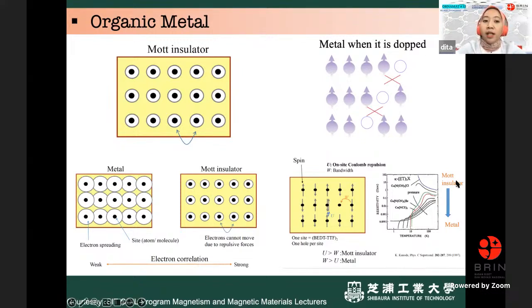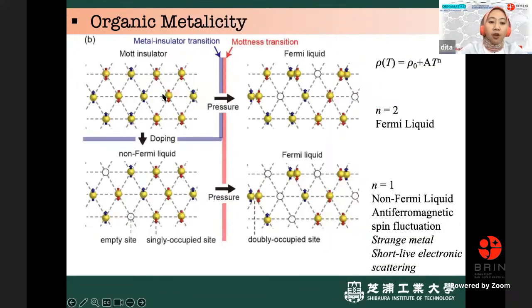In the organic metal, the condition is more the second one. So you can see here a transition from a Mott insulating state to the metallic state by pressure in the organic conductor. If we have a Mott insulating state and we pressurize it, it will become a metal, usually modeled by a Fermi liquid model. And we have this temperature dependence of resistivity. Fermi liquid usually follows the temperature square of resistivity.